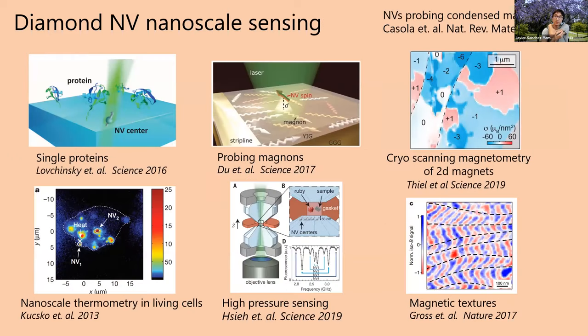Just to flash a couple of examples of people using NV centers for various types of nanoscale sensing: it's been used to detect single proteins, and to probe spin waves in magnetic materials. Some more recent interesting work studies two-dimensional magnetic materials. This is cryo-scanning magnetometry work from the group of Patrick Maletinsky, where they can see the domain structure of the 2D magnet. What's cool is you can see the scale bar, 1 micron. This is a scanning NV center, where they scan a diamond with a single NV center in it above a sample. They can map out the magnetic fields with tens of nanometers resolution.